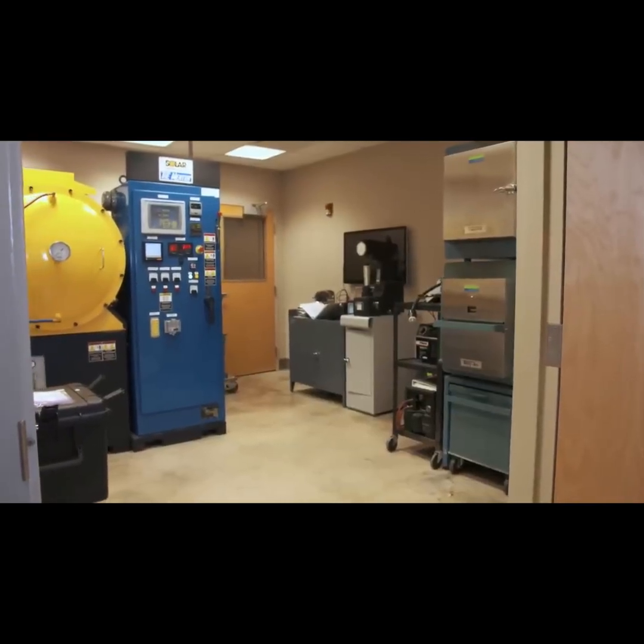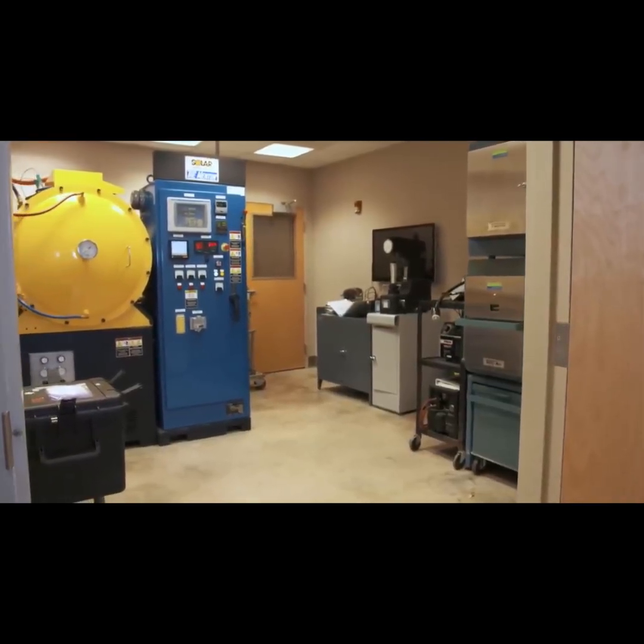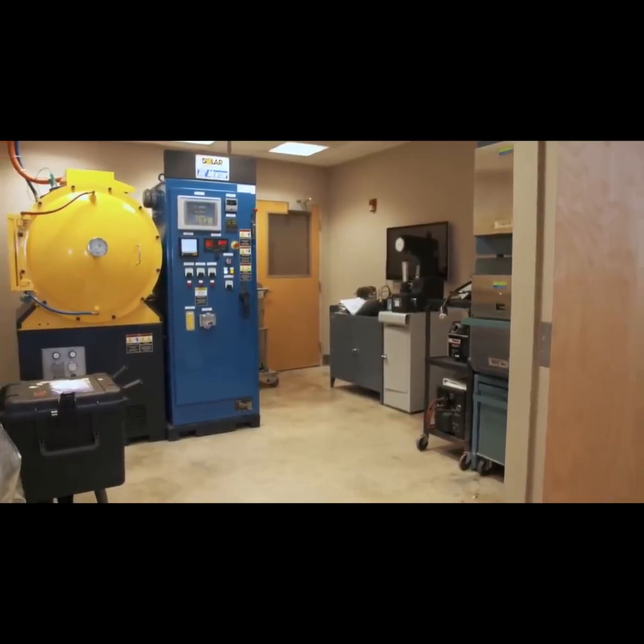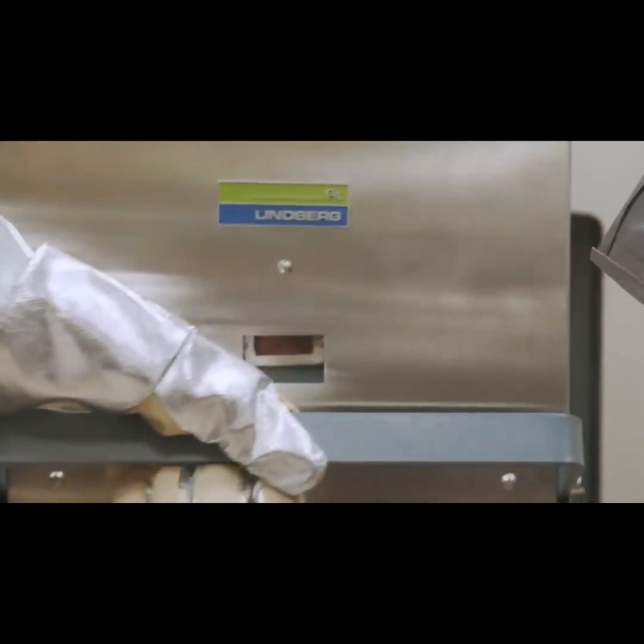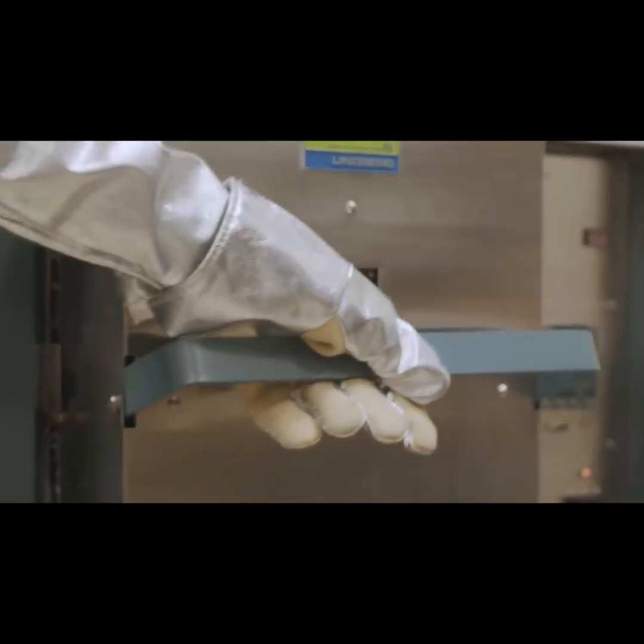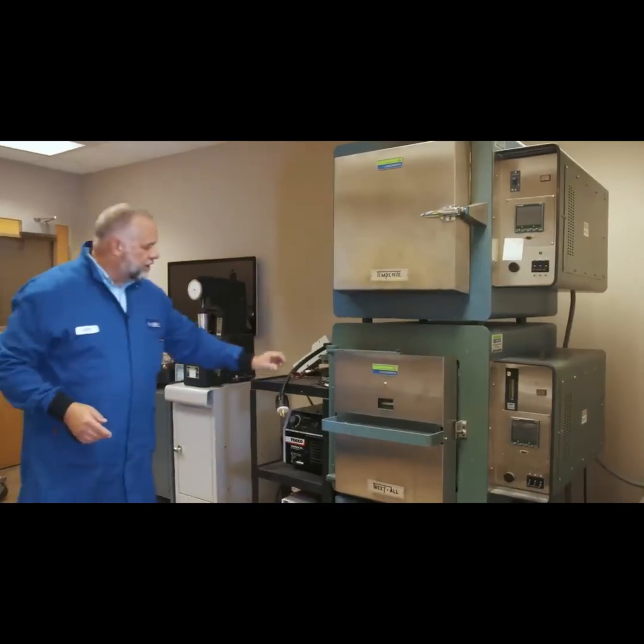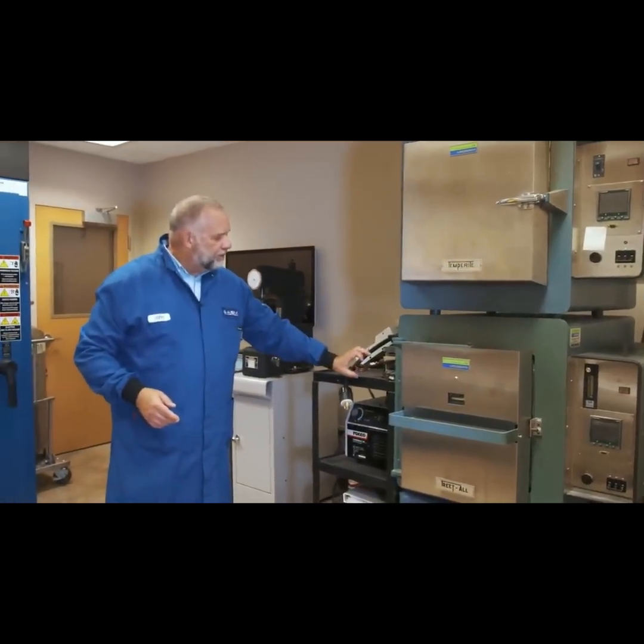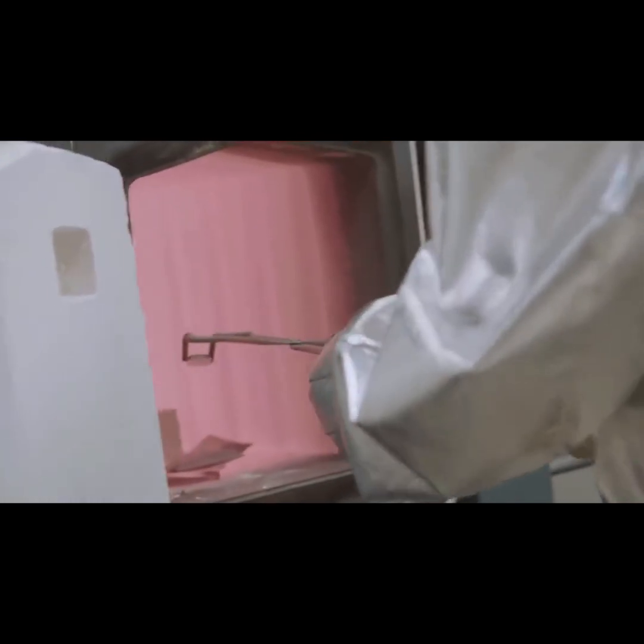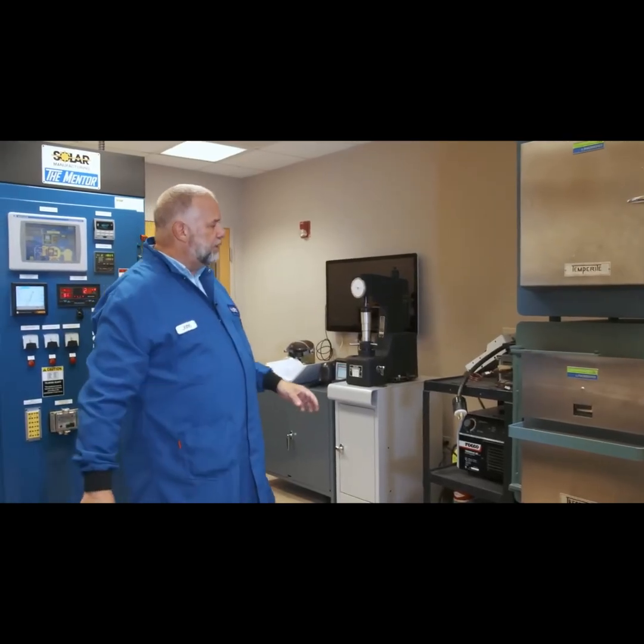So this is our heat treat lab. Before 2013, we basically had some box furnaces to do different temperatures. These can do up to 1100 degree temperatures. This is a Tocco induction hardener, and if you put a sample in here and you reverse the current back and forth rapidly, you can generate some heat on the surface of the part.